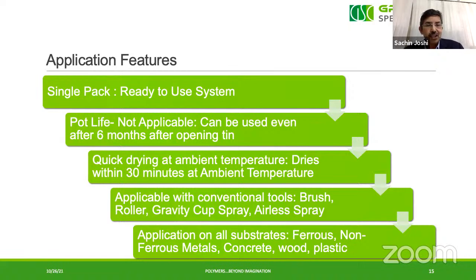Secondly, application. It doesn't require any specific pumps or heating systems or nozzles from Germany or USA. No, conventional brush, roller, gravity cup spray, airless spray, you can apply this absolutely with no problem. And you can apply on all substrates. You can apply on ferrous, carbon steel, mild steel, non-ferrous, aluminum, copper, even on galvanized steel directly you can apply this coating without primer. On concrete, on wood and plastic.